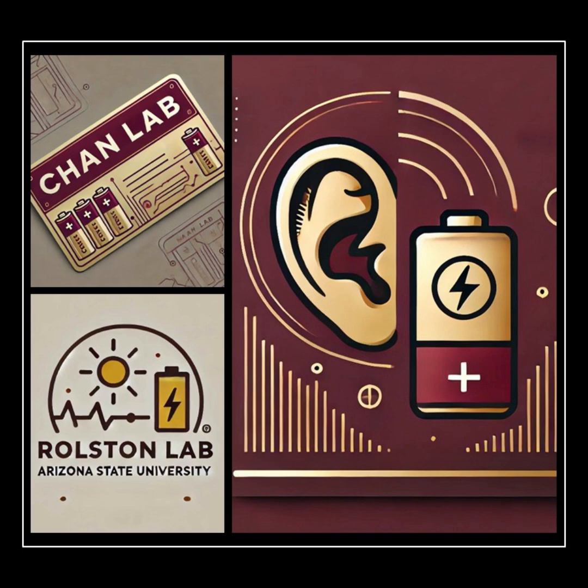How does it compare? Well, here's the interesting comparison they made. The level of cleaning they achieved after 20 minutes with this open-air plasma was comparable to the surface state you'd get just 3 minutes after cleaning it with a much harsher, more complex vacuum-based argon ion sputtering method. Whoa. So similar cleanliness, but without the vacuum chamber and all that hassle. Exactly. That's the key takeaway from a manufacturing potential standpoint. Achieving that level of clean in an open-air setup is a really big step.